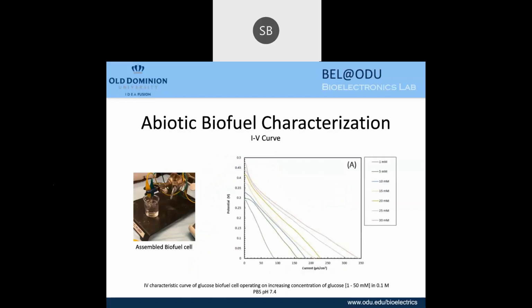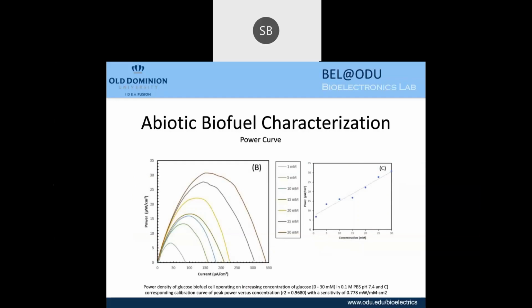By combining anode and cathode, we were able to see the performance of the biofuel cell. We carried this out using linear sweep voltammetry, which resulted in a linear range of 1 to 30 millimolar. This shows the calibration curve of 0.968 with a sensitivity of 0.778.